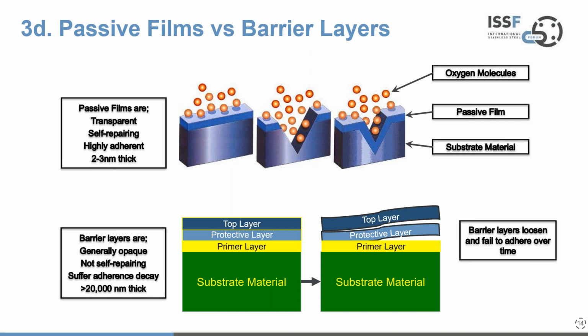Whereas with barrier layers, you generally have to apply several layers: a primer layer, a protective layer, and a top layer on top of that. Over time, they loosen, they get scratched, they don't self-repair. So you have lots of problems. And whilst they're very much thicker, once you start to damage them, you're actually inviting corrosion and decay to occur. So yes, they're probably cheap and easy, but they require a lot of attention as well.